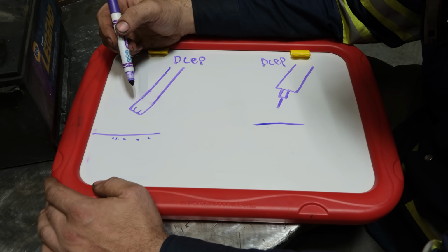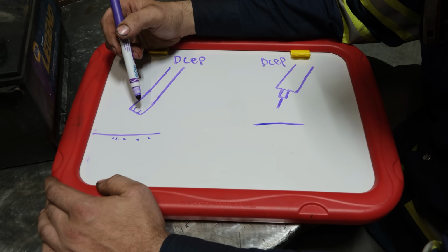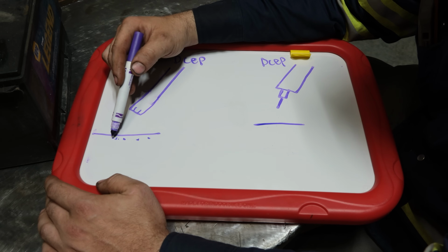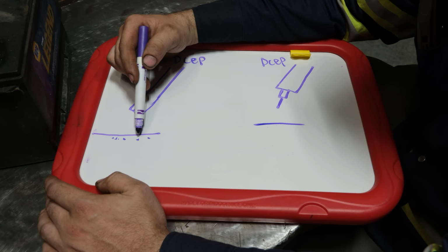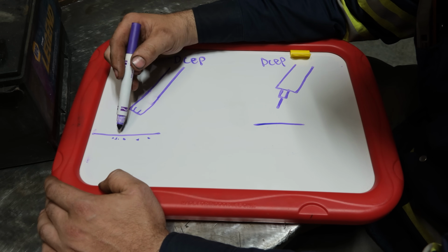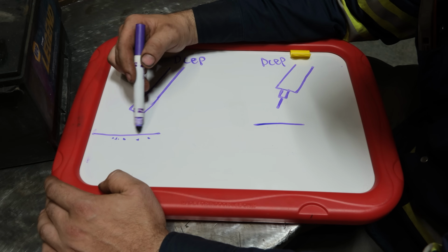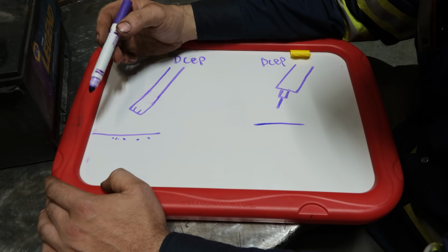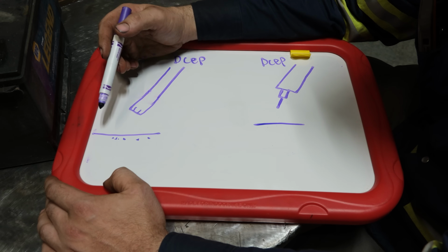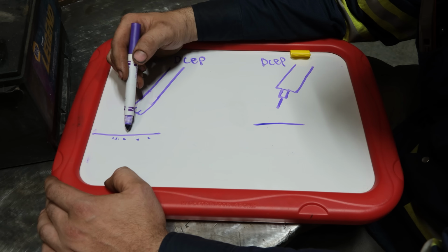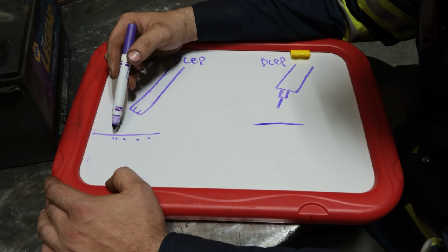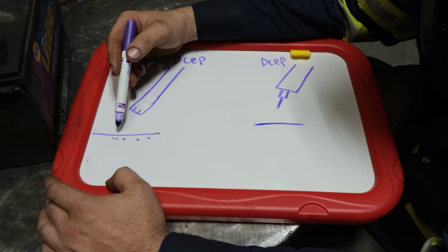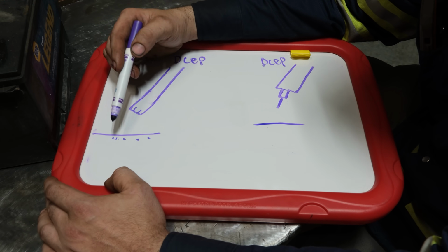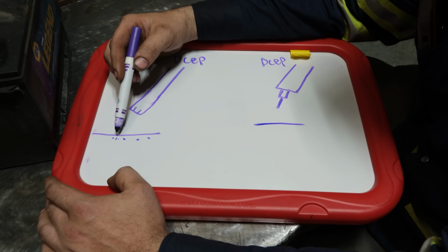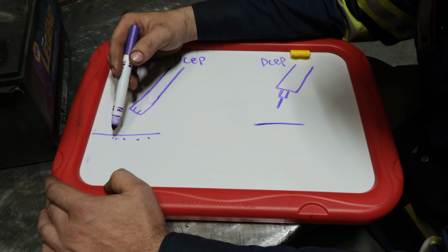Now, there's actually some benefit to running EP. The first one being that the act of the electrons jumping from the base material to the tip will actually help break down the surface oxide on the material. If you've ever TIG welded aluminum, you know for a fact that those electrons actually strip off the oxide layer on the aluminum, which makes welding clean welds on aluminum possible and fairly easy. Well, it actually does the same effect on steel, believe it or not. It does strip some of the surface contaminants.